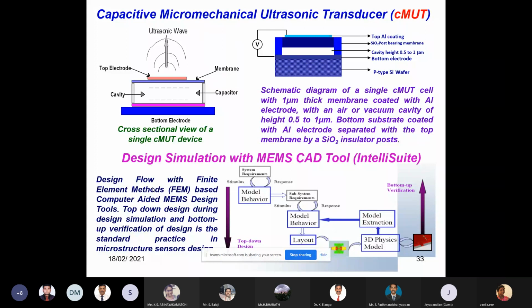The membrane is 1 micron thickness, and the circular part is 50 micron diameter. If you apply a DC potential, the membrane deflects towards the bottom substrate. Then, applying a simultaneous AC potential, it will vibrate. To have maximum vibration, a DC potential is applied, but you should not touch the bottom surface. That is the collapse voltage. If it touches the bottom, it won't work. Nearing the bottom, applying an AC potential gives maximum amplitude, and then the maximum signal strength can go out.